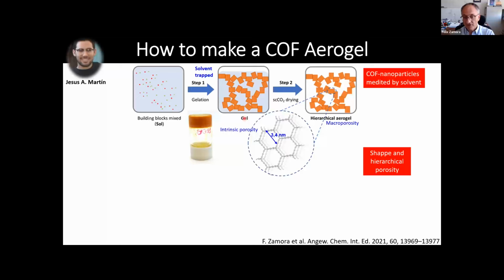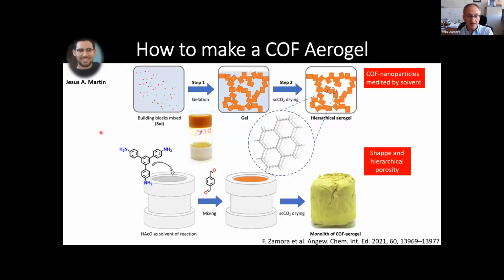So this was possible to do with three different reactions. And when we confine this reaction, the formation of the gel, in a vessel with a specific shape, what we observe is that the shape was retained upon drying. So we were able to pass from the gel to the aerogel, producing these shapes, in here we produce monoliths, okay, of a COF aerogel.